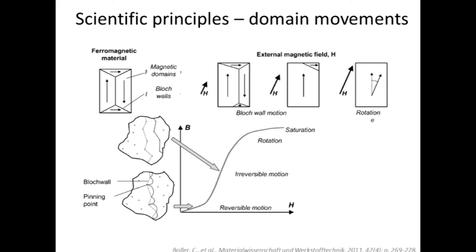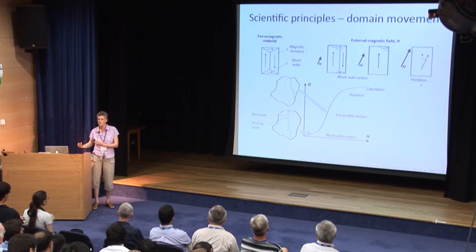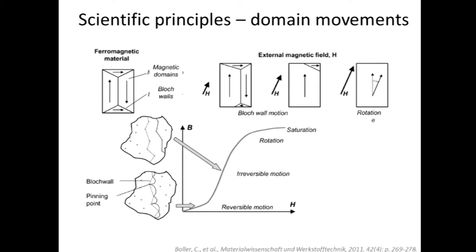What's more important is how this relates to microstructure. If we go through a BH curve, we need to visualise the idea of magnetic domains in the material — to go through the BH curve you have to move magnetic domain walls. Domain walls, as they move, interact with microstructural features that act as pinning points, so we get the magnetic behaviour linked to microstructure because microstructural features pin magnetic domain walls. What we've been looking at so far is the initial part of the curve where the domain walls haven't been moving a great distance — they've just been wobbling. As you apply higher fields, you start to overcome pinning points. The concept that becomes important is how strong the pinning points are and how many we overcome as we apply different field levels — and if we can reverse-engineer that, we can say for a given field we're overcoming specific microstructural features.